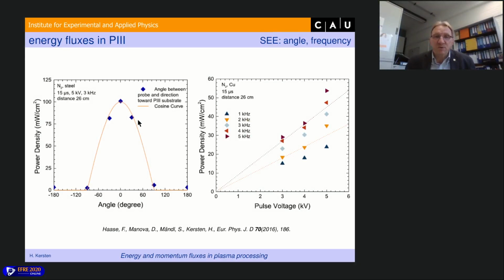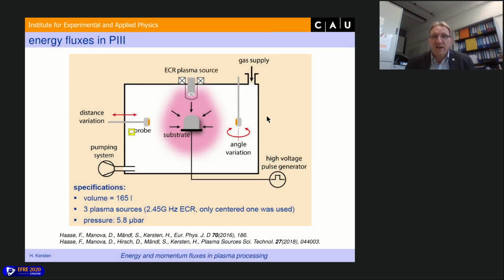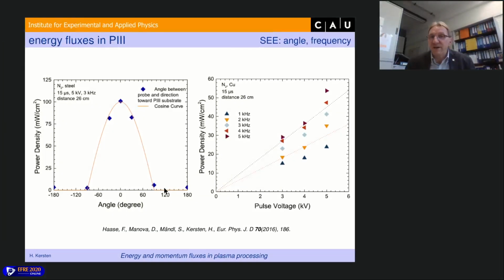And we measured here with our thermal probe, for instance, the angular distribution of the energy, and that's clear. 0 means it is face to face, and 180 means it is the opposite direction. So in the opposite direction, we don't measure any energy influx, and we measure the maximum energy influx at 0 angle. It's clear. And if you increase the pulse voltage or the frequency of our pulse, then we also increase the energy influx, which you would also expect.